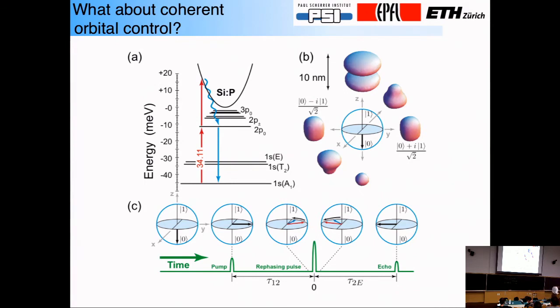And now we're getting back to the physics here. So now all we have to do is relabel the Bloch sphere. What we're going to try to do is see if we can create coherent superpositions of these excited atomic states. Let's say I want to create wacky wave functions, which are somewhere between a 1s and 2p-like wave function. Here's my 2p, these two pancakes. Here's my little sphere. And then I go to the Bloch sphere, and I get all these funny shapes here. But I have a Bloch sphere, as I did before. So all I need to do is, again, pump the material with a pi/2 pulse, get it to the equator, put my rephasing pulse on, and look for the echo. And now we're doing this optically.